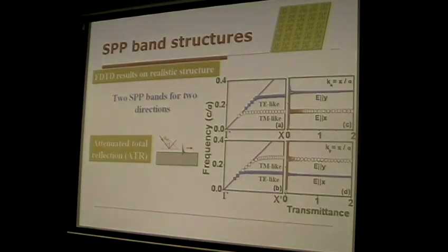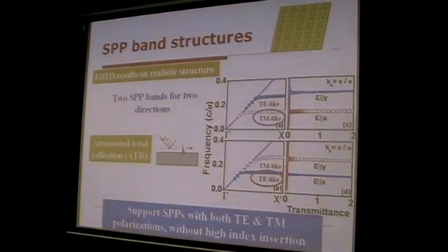We employ the idea of an ATR technique to identify the polarization properties of this SPP band. And we found that for this frequency, for this direction, the SPP is TE-like polarized. For this direction, this is TM-like, and this is TE-like. So that means this structure can support surface plasmon polaritons with both TE and TM polarization without high index insertion.